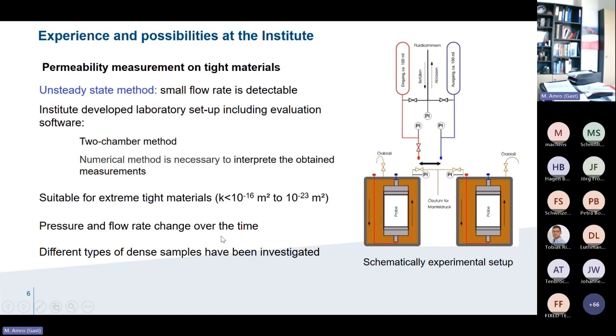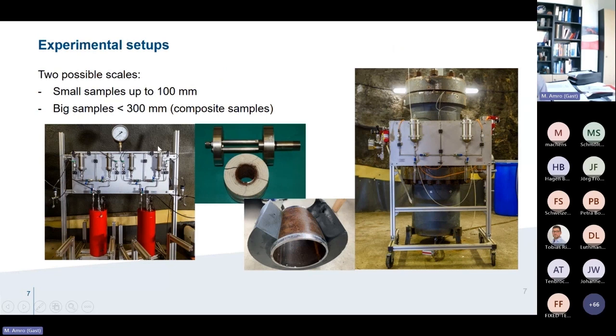So the pressure and flow rate change over time can be recorded, and we can use different types of samples, not only salt. We can use, of course, cement and so on. And we investigated a lot of samples, mainly for European countries here. So again, this is the system I introduced to you schematically. Within this system, we can measure small samples. Small samples means a diameter of 100 millimeter. For example, here such cores. You have here 100 millimeter in diameter. We can measure up to 200 millimeters. This is one of the samples we have measured here.